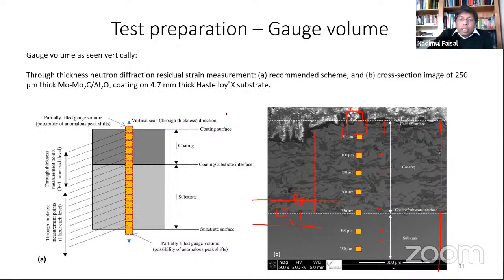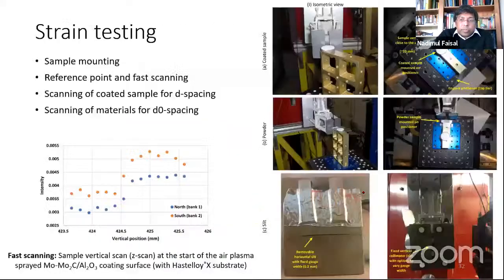And the coating part takes a lot of time. For these 4 or 5 points, you may end up spending 24 hours of continuous diffraction. However, for the substrate, you can take less time, maybe an hour or half an hour or so. Again, these decisions are taken based on the material. So in our case, we typically take 3 to 4 hours per point to diffract and get nice, useful data for analysis.